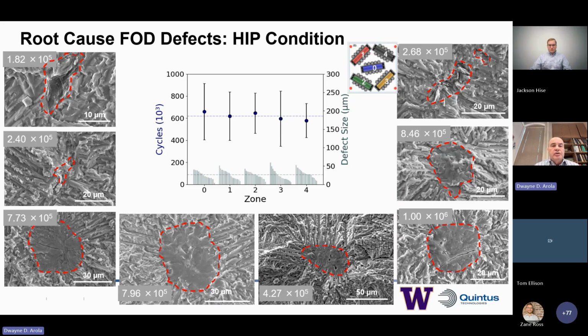And again, we show the distribution of some examples of representative defects that were found responsible for the initiation of failure. You can see that none of those are lack of fusion. So we're extremely happy about this, and it's actually increased our efforts to try to understand these major sources and how they propagate into mainstream production.